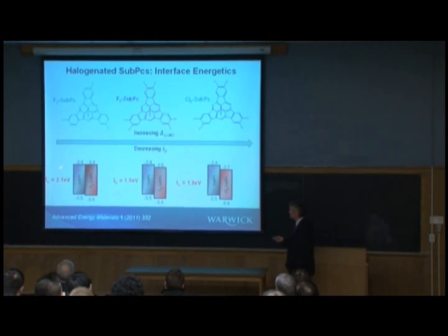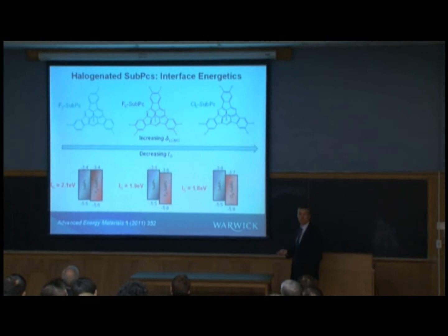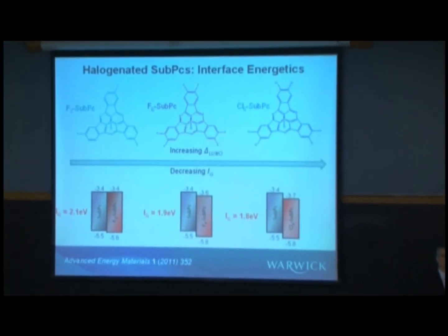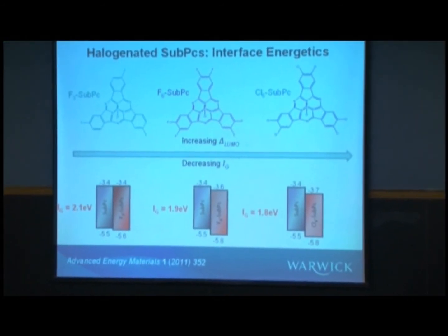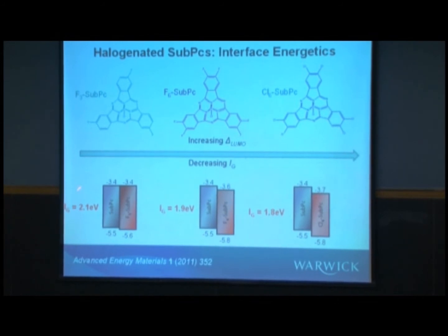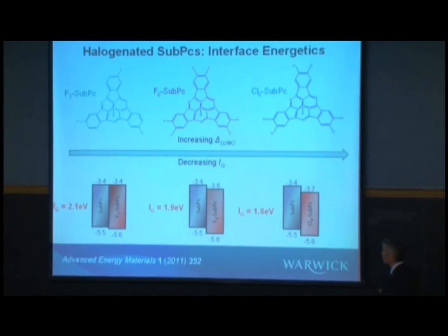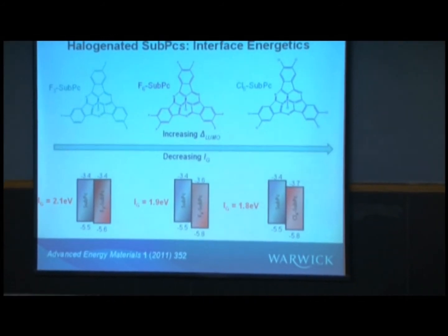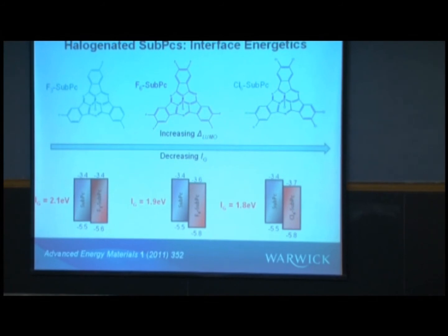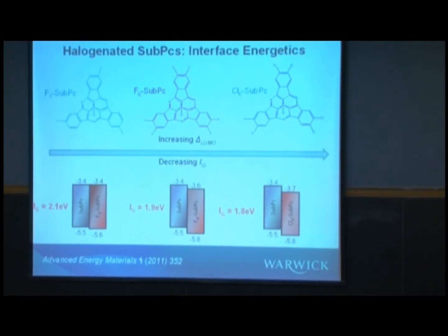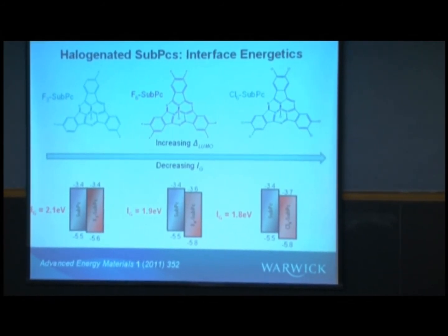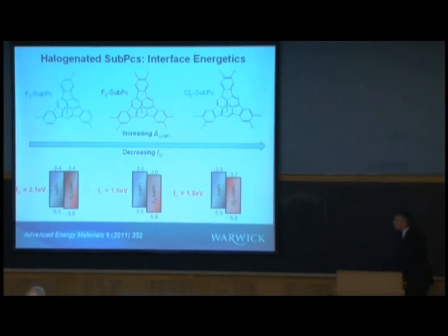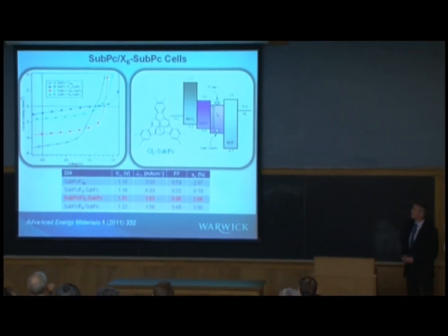But importantly, what you see here on the left-hand side, there is really no energy offset. You can't dissociate the excitons very efficiently, so that device is just not going to work in a very practical way. You might have a high interface gap, but the rest of the energetics don't work. Whereas if we go across this diagram, then we have both good energetics for the dissociation and a high interface gap energy. And that does indeed translate into good performance, otherwise I wouldn't be showing you.